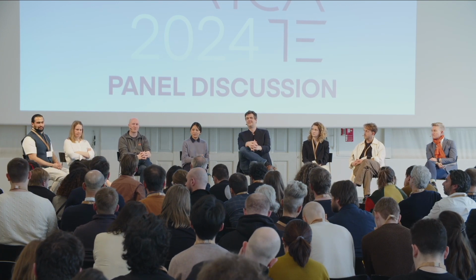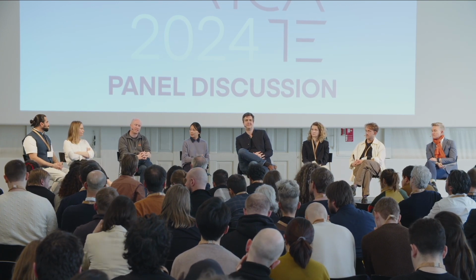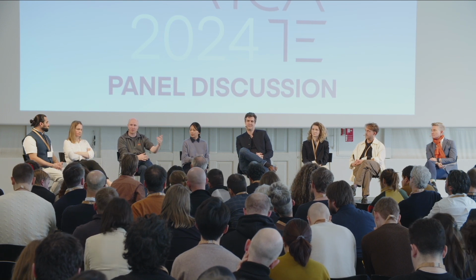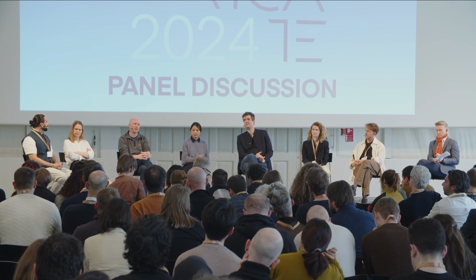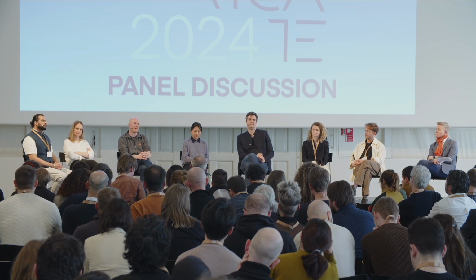I fully agree with you on that, by the way. It's just a matter of taking one step at a time. Looking back a couple of years, our mixes from various material providers had a huge cement content, right? And that isn't good. And they had fibers in them and whatnot. And now we've moved towards conventional mixes where the cement content is comparable to conventional concrete, it's in the same norm, right? Larger aggregate sizes, taking down the cement size.